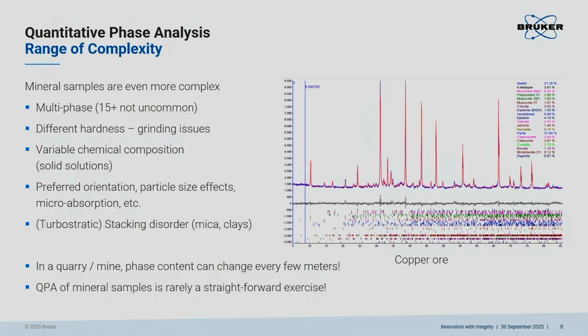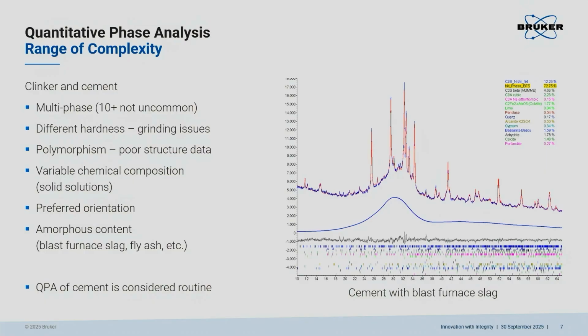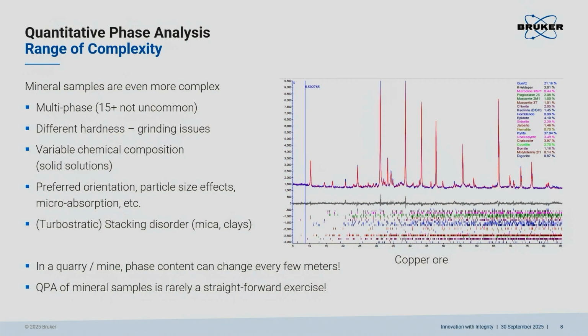Preferred orientation, yeah, we heard about that yesterday. Amorphous content. Still, clinker and cement is certainly routine these days. A different example, for example, here, a mineral sample from a quarry or a mine, I don't remember, 15 plus phases, absolutely not uncommon in such industries. Here, the different hardness is a big issue. Remember, the destroying of soft phases, like here, quartz, next to, let's say, a clay. So the sample preparation becomes a huge issue here. Variable composition, the same thing, micro absorption, a particular problem, not so much in cement, but in general. This is actually a contribution to error I want to focus a lot on later. Stacking disorder, sometimes turbostratic. So with the traditional Rietveld method, it's all but easy. It is never a straightforward exercise.